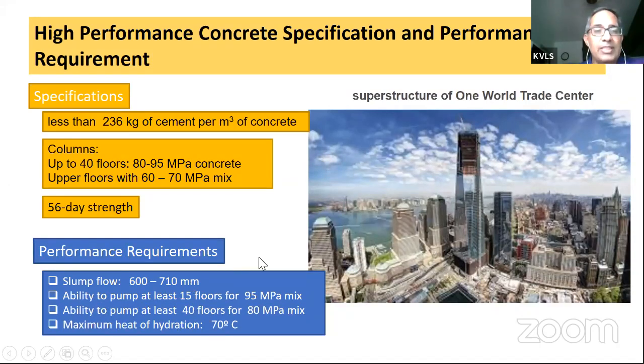The performance requirement was that, of course, there was some slump flow requirement, but also the ability to pump. Concrete should be pumpable for 15 floors for the 95 megapascal mix, and the 80 megapascal mix should be pumpable for 40 floors. This was put in as a performance requirement for fresh concrete. So whatever concrete came on site, it should be pumpable. That is, I should be able to lift it. If it is an 80 megapascal concrete mix, I should be able to lift it 40 floors in a single pump. So that is a performance requirement of this concrete.